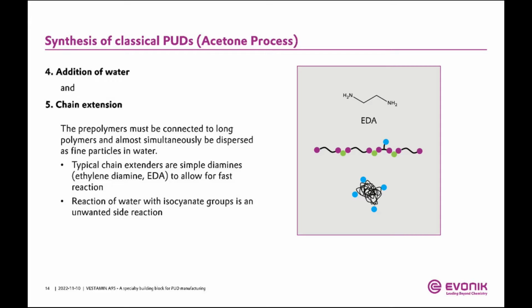If you do the chain extension too early and then you wait forever, your molecular weight will build up to very, very high dimensions and you cannot disperse it anymore. So it's a bad idea to start with number 5 and then forget about the water. On the other hand, when you just add the water and forget about the chain extension, well, the water will attack your isocyanate groups and decompose the isocyanate. So it is really important that you have both steps in mind together.